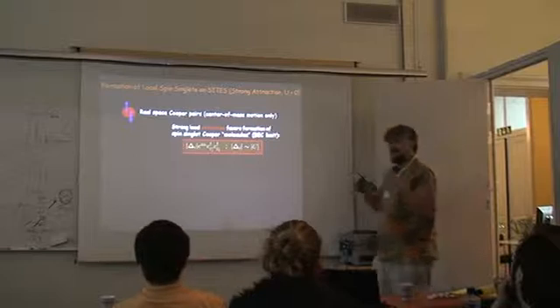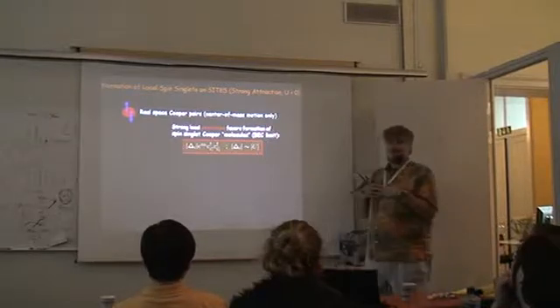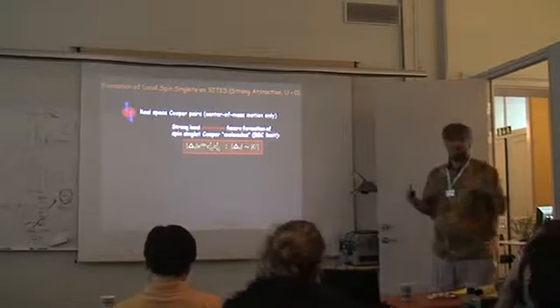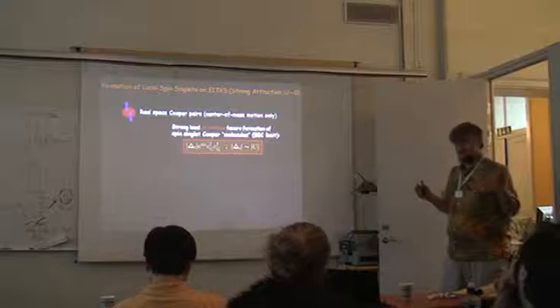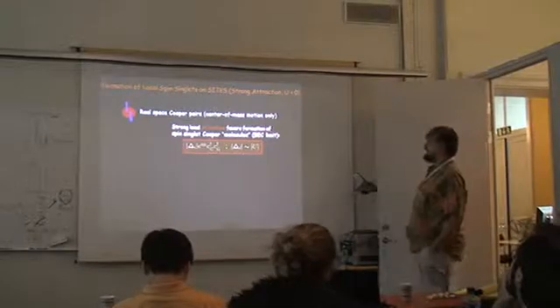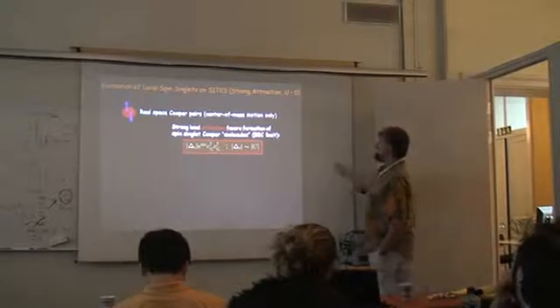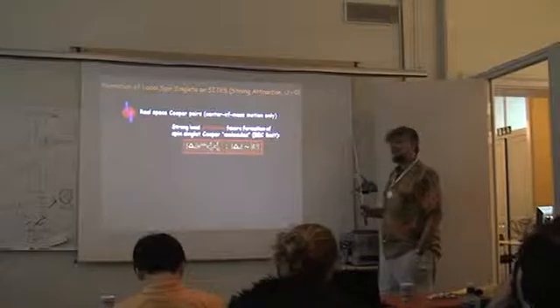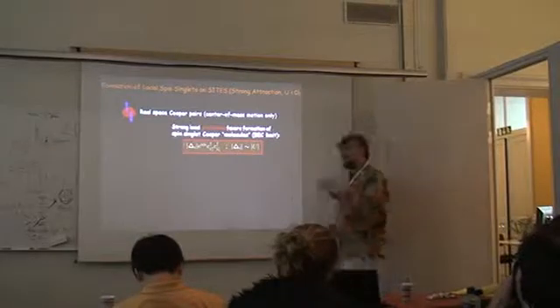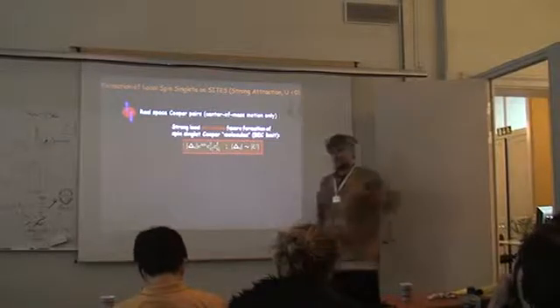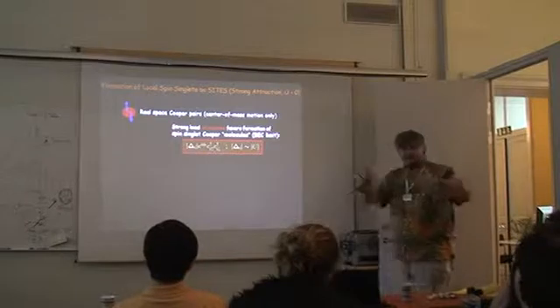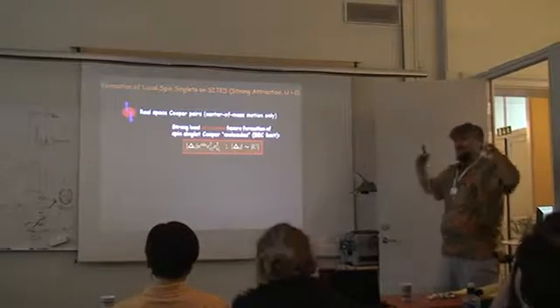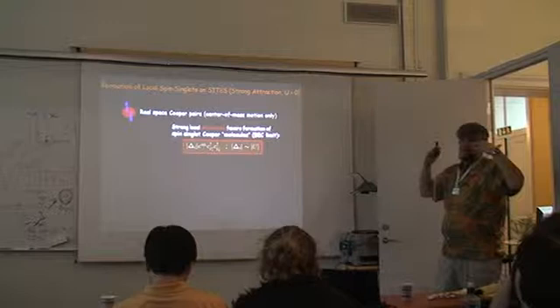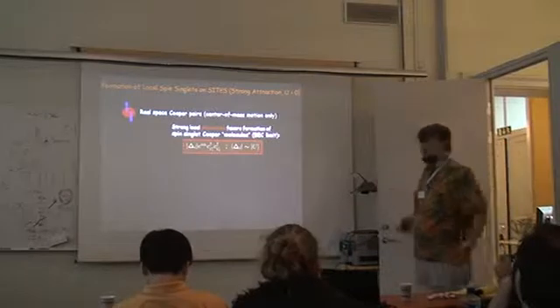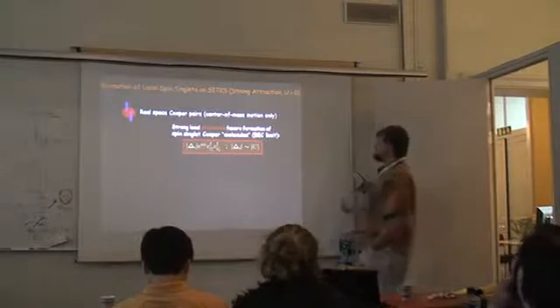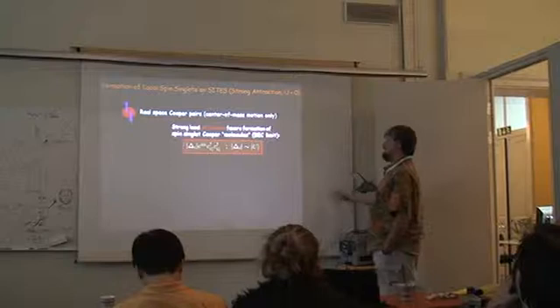Then we agree on general doping and the general shape of the band; this is a superconductor, minus the 2D provisions of Kosterlitz-Thouless and so on. What happens when we have negative U, but the negative U is very strong, meaning it's the strongest energy scale in the problem, larger than kinetic energy or any residual Coulomb interactions that are due to insufficiently screened original bare Coulomb interaction?